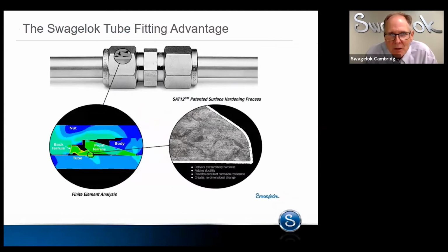Okay, what we have here is, again, a depiction, lower left, of finite element analysis. This shows a cutaway of the ferrules inside the tube fitting contacting the tube and a cross-sectional view on the right at the nose position of the back or rear ferrule that has gone through the carburization process. The diffusion of carbon has gone into the surface of the back ferrule and is not a layer applied on top of the ferrule. That white ribbon in the lower right is the consistent effect of carbon diffused into the surface, providing incredible hardness and corrosion resistance without dimensional change while retaining ductility of the material.